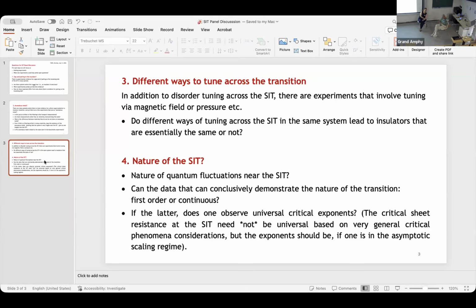Would somebody like to conclude? How does one define a first order transition in the SIT? Is it a discontinuity in the ground state energy? So what we observe in indium oxide looking at superfluid stiffness as a function of T_c is that it does not diverge as a power law at the critical disorder. Instead, it flattens and saturates to a certain value, 0.5 Kelvin, which is not small, because I said before that we could measure superfluid stiffness in magnetic field. And this is the point: T_c, as well as the superfluid stiffness, saturates at typically 0.5 Kelvin in amorphous indium oxide.